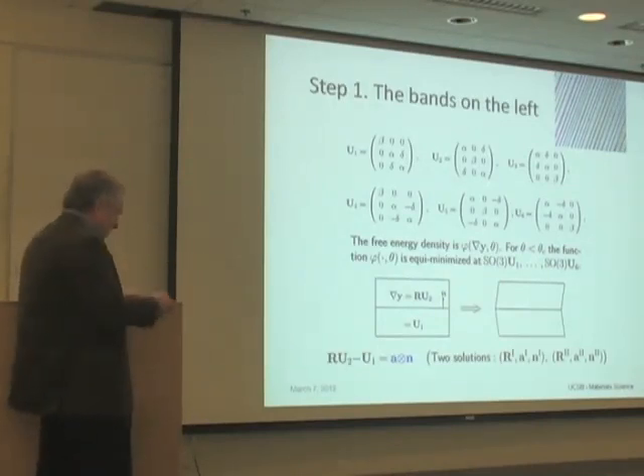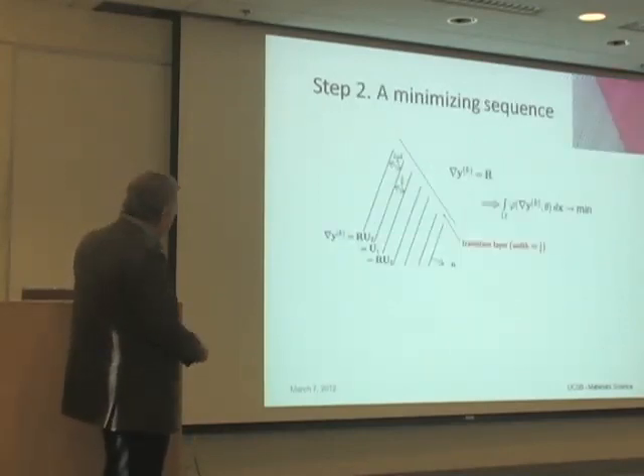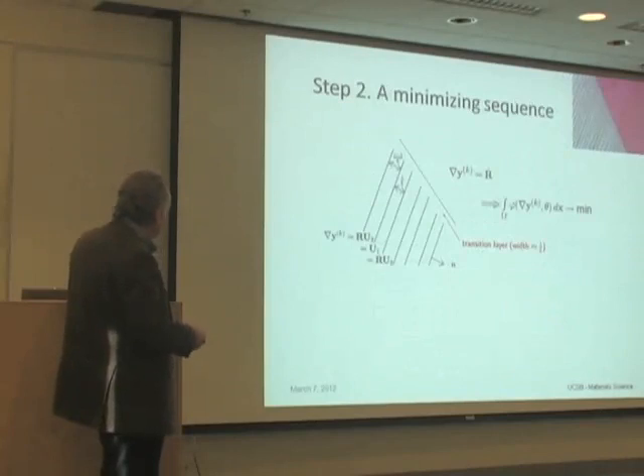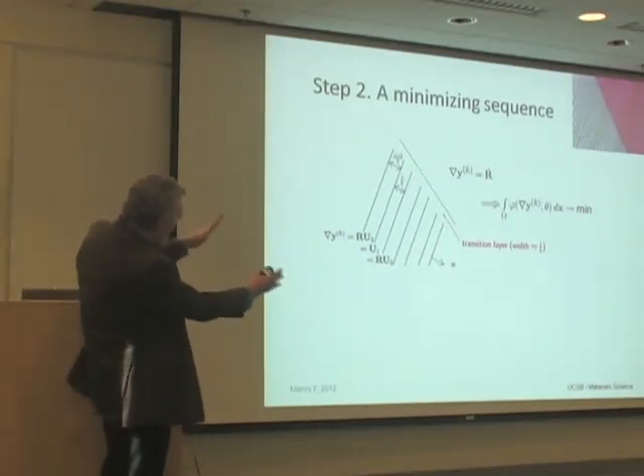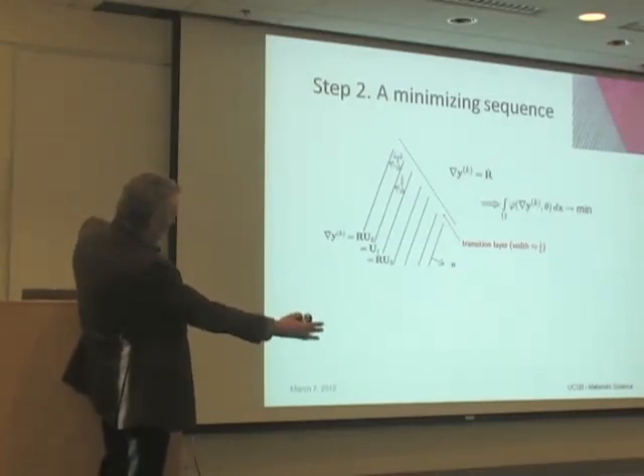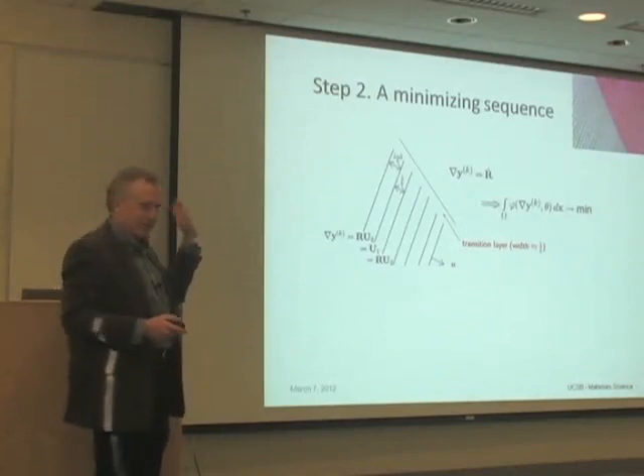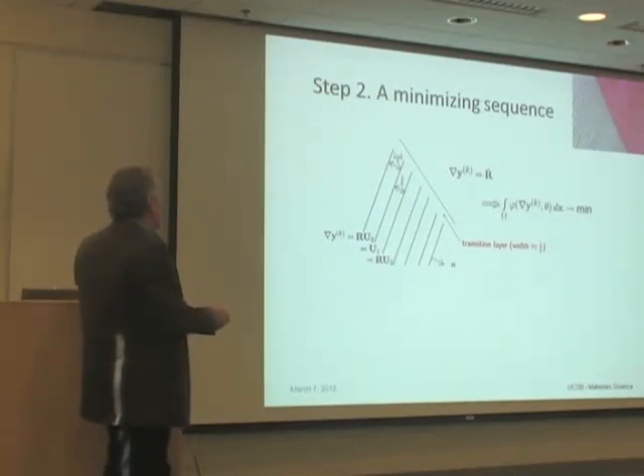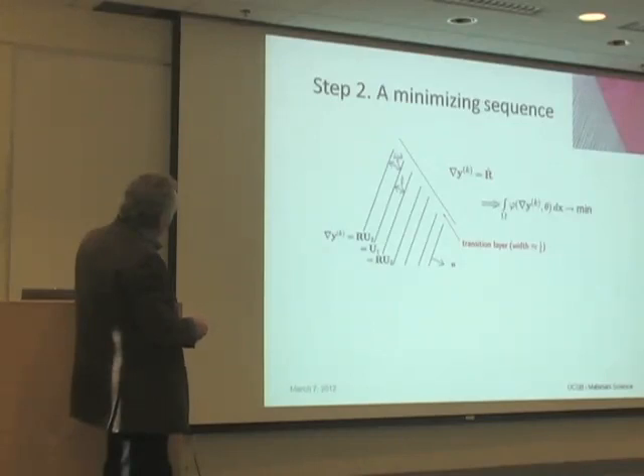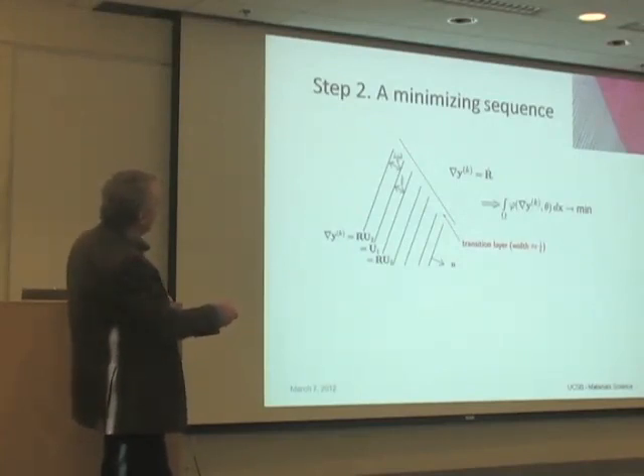Okay. Now, take those two deformation gradients and layer them over here, alternating with a certain volume fraction lambda. And I introduce another parameter, k, here. When k gets large, this gets finer and finer. So it allows me to control the fineness independent of the volume fraction. And over here, you put a state which corresponds to the austenite energy well. And you first find that there's no continuous deformation which has this value here and these values over here. So you're forced to put in a transition layer. That's what the real material does, too. It puts in a transition layer. And there's elastic energy in this transition layer.